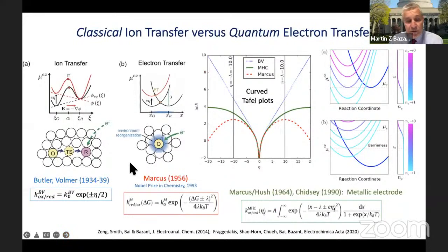On that topic, I'll just briefly tell you a bit about electrochemical reaction rate theories, which are very important in this work, and which we would like to learn from images. That's where I'm going with this. So first of all, the standard model of electrochemical reaction rates is very simply Arrhenius reaction kinetics, where you basically think of some charge, maybe an ion, hopping over a barrier, driven by the so-called overpotential, which is sort of the bias of the reaction tilting the barrier by applying an electric field across that interface. So that's a very classical approach.